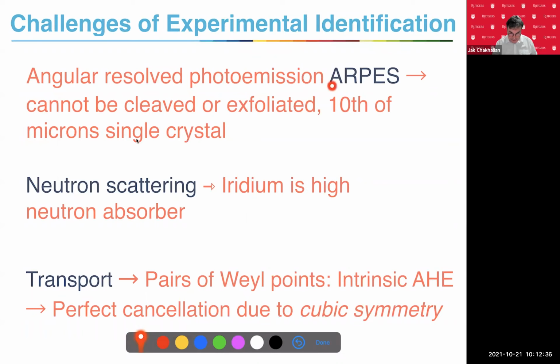ARPES is not possible because so far people could make only 10 micron size single crystals, very, very small. Neutron scattering, impossible because iridium is a very high neutron absorber. And transport, oh, bummer. You thought you would have some exotic effects, but this structure is cubic. Every pair of Weyl points in the cubic structure basically cancels out, because plus minus in the cubic symmetry gives you nothing. The sum of Chern numbers, the topological charge, has been zero. So due to the cubic symmetry, even transport cannot reveal much.